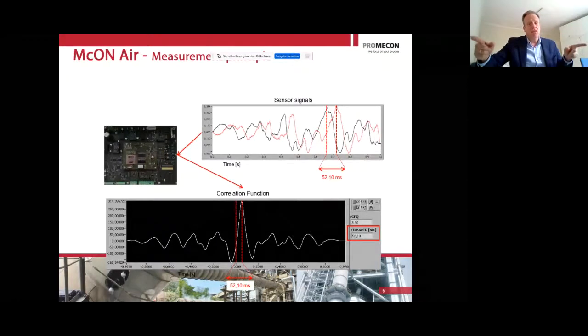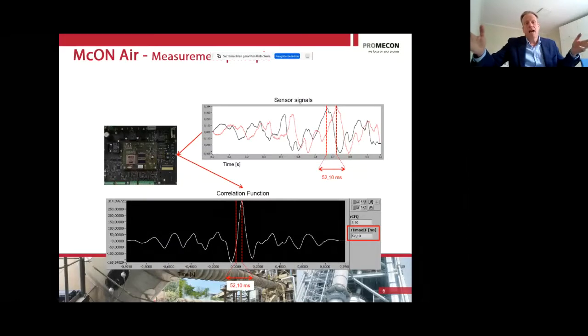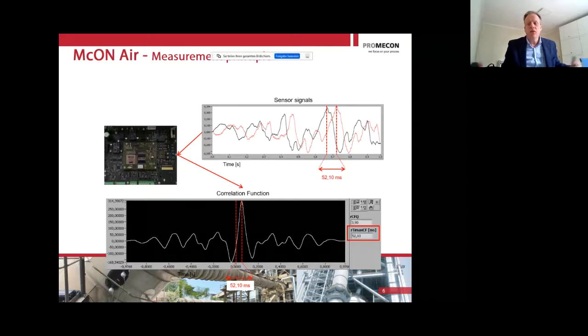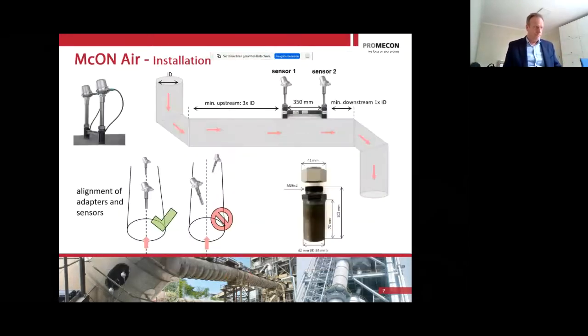And now we have the distance of the sensor, for example, 350 millimeters. We divide by the time shift and we get a velocity. So we can measure raw gas, process gas velocity. Taking the cross-sectional area of the duct, we can then multiply with this area and arrive at volumetric actual flow, right? Now, if you take the gas temperature and the barometric pressure, you can then also calculate the standardized gas flow on that location. That's all. It's a very simple way to measure.